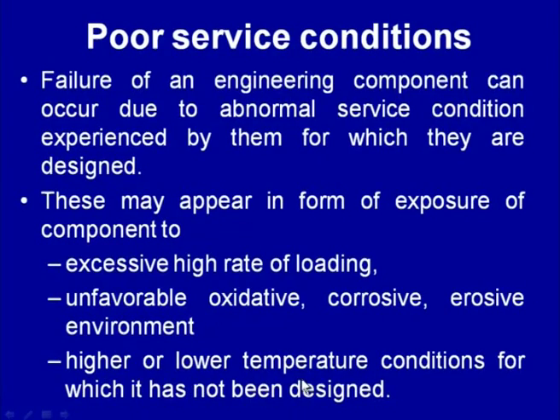So, exposure to high temperature will lead to deterioration in mechanical performance, and that can lead to failure due to either elastic or plastic deformation or complete fracture. Similarly, exposure to lower temperature can lead to catastrophic failure due to the loss of toughness of the material, especially in the case of weld joints.